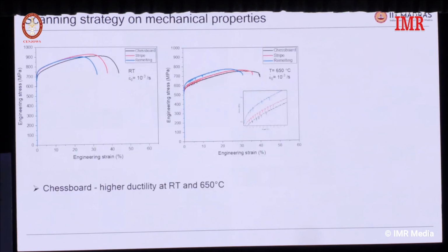So here I am going to give the properties at room temperature and high temperature. They are done at a constant strain rate of 10 to the power of -3 per second. What you can see is that just because we have changed the scanning strategy, we see a difference in the properties, where the chessboard gives almost a higher elongation as compared to the other 2 scanning strategies. Similarly, in terms of high temperature strength, the chessboard is slightly lower, but it has a better ductility.